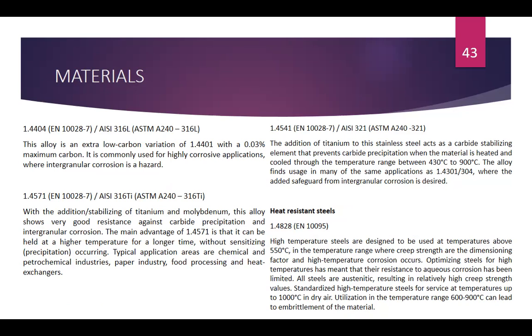In the temperature range where creep strength is the dimensioning factor and high temperature corrosion occurs. Optimizing steels for high temperature has meant that their resistance to aqueous corrosion has been limited. All steels are austenitic, resulting in relatively high creep strength values. Standardized high temperature steels for service at temperatures up to 1000 C in dry air. Utilization in the temperature range 600 to 900 C can lead to embrittlement of the material.